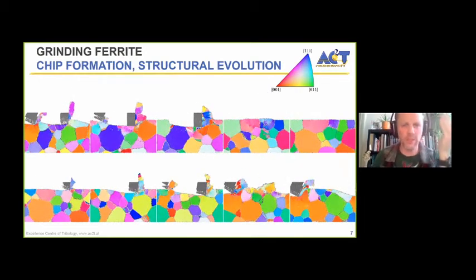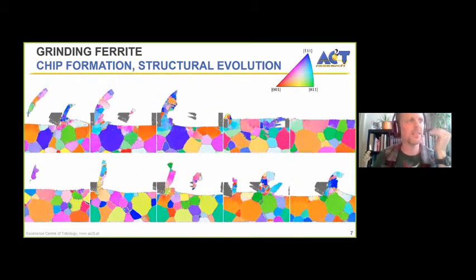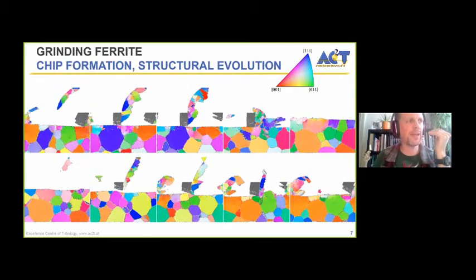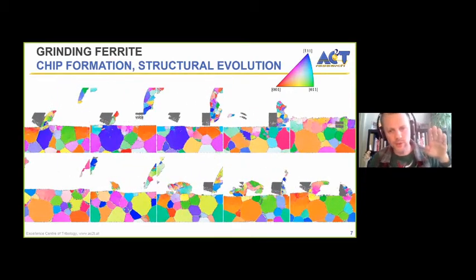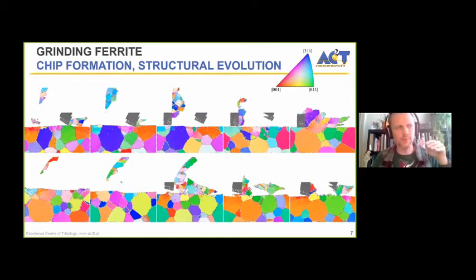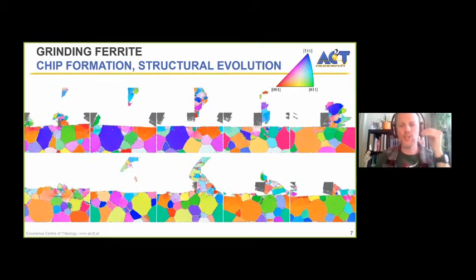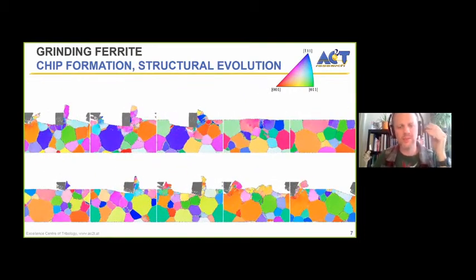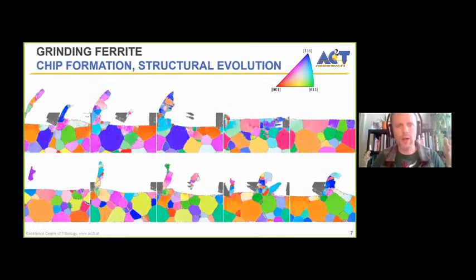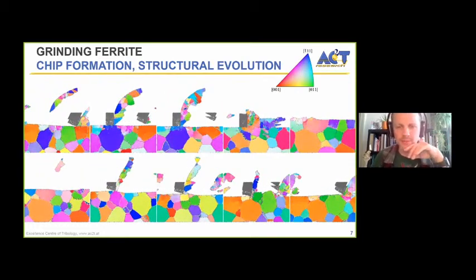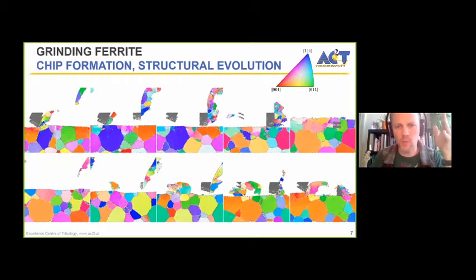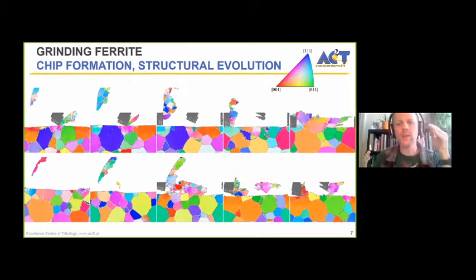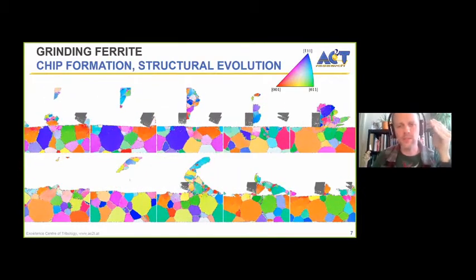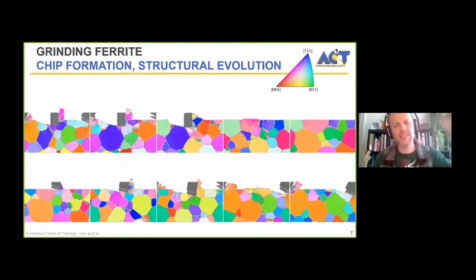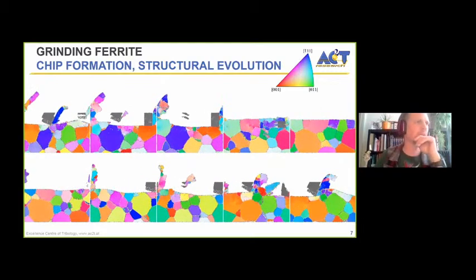because these slices are only 2 monolayers thick. It's because my abrasives are going at a slight angle to the x-axis of my system so that they scan a larger portion of the system more evenly, because as you saw before, it's periodic. So they go out, let's say, the right side of the system, they come back in Pac-Man wise on the left side, and I don't want them to keep grinding in their own grind marks. So they will be moving slightly up and basically scanning the entire system.